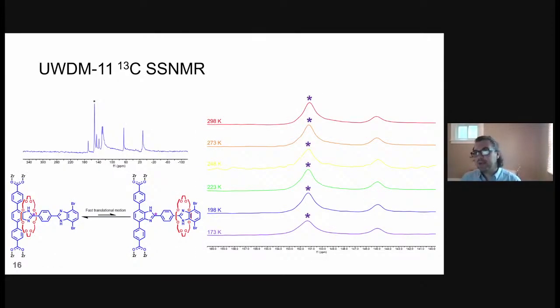So we started off by activating the MOF and measuring the carbon-13 solid state NMR. As we can see, this peak here, which is nice and strong, is our carbon-13 enriched environment. As we cool down, we start at room temperature with one peak corresponding to fast translational motion. And even at 173 Kelvin, which is the limit of our solid state NMR, we still simply see one peak.